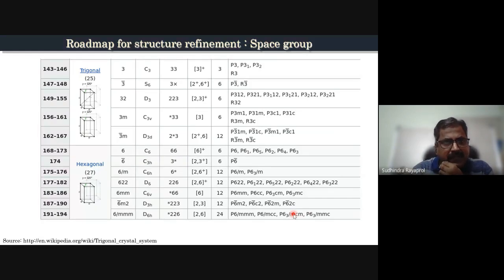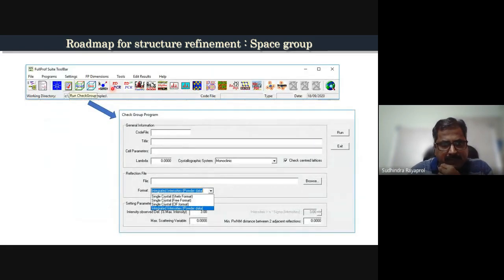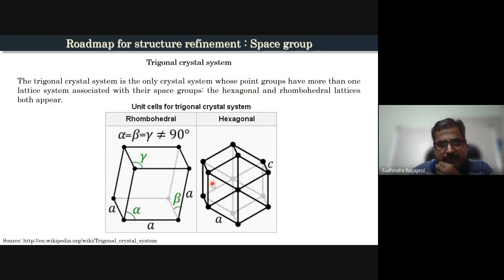The next step is to identify the space group. Now you know from the refinement that it is a hexagonal structure or a trigonal structure, so it can be any of these space groups. There is a program called Checkgroup in the Fullprof suite. You can use integrated intensities. You can use WinPLOTR and the raw data file to get the integrated intensities. Using these integrated intensities for the powder data, you can ask the program to suggest some space groups. Depending on the space groups, you know what type of crystal system you have.